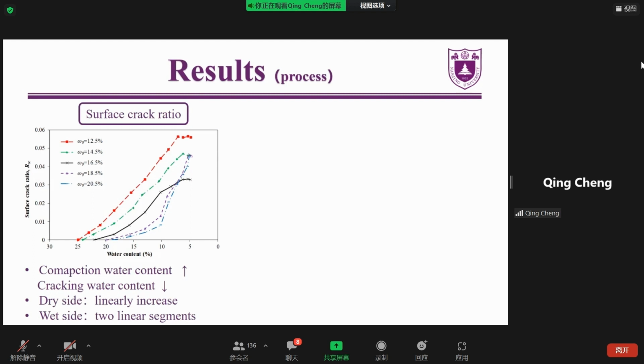Moreover, we can also find that during drying, the surface crack ratio of all the samples shows an increasing trend. Specifically, for the soil samples compacted on the dry side and at the optimum water content with bimodal pore size distributions, the surface crack ratio increases almost linearly with the decreasing water content.